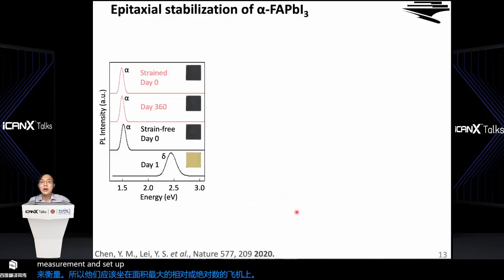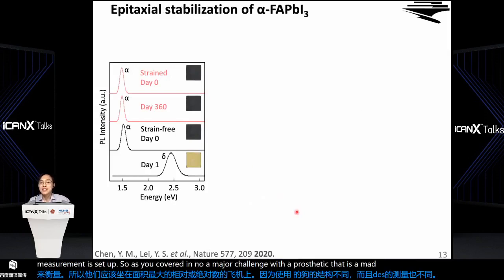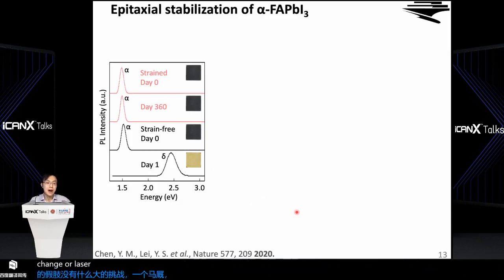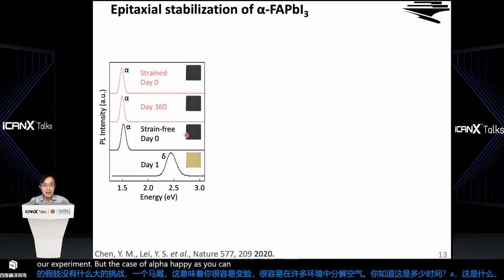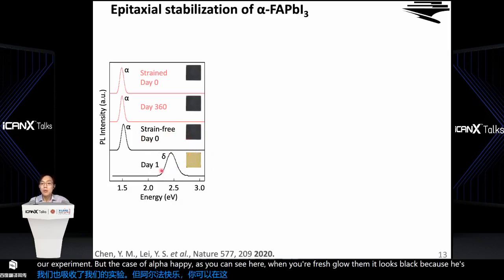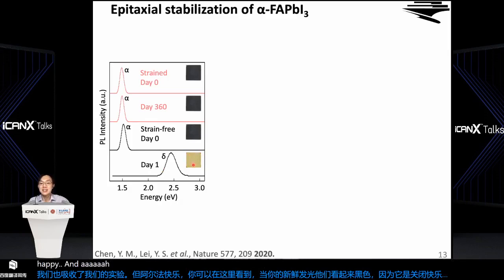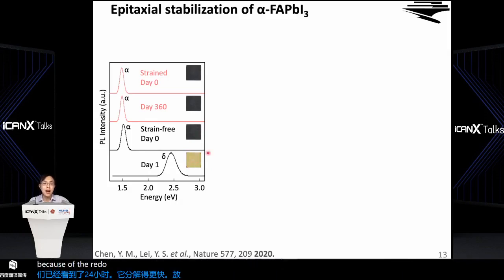As you probably know, a major challenge with this perovskite is that it's metastable. That means it will easily change phase or easily decompose in air in an ambient environment in a very short amount of time. This is what we also observe in our experiment. For the case of alpha FAPI, as you can see here, when you first grow it, it looks black because it's alpha FAPI. And after about 1 day, within 24 hours, it decomposes quickly into this yellow phase, delta FAPI. And this delta FAPI is less interesting compared to alpha FAPI because of the reduced carrier transport properties.